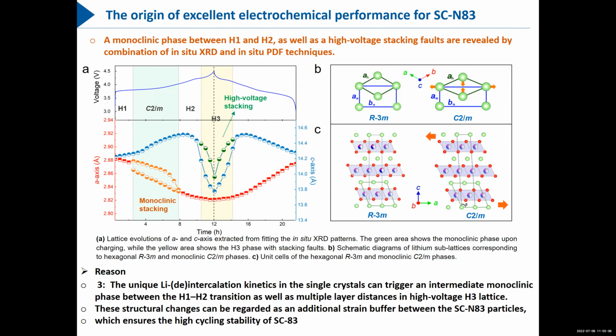So what is the reason for these two phase transitions? Now we know that if the phase transition goes from the H1 phase to the H2 phase, the lattice parameter change is huge. If it changes directly from H1 to H2, the lattice parameter change is very huge, and a huge lattice parameter change just means huge microstrain. So we believe that if there is an intermediate monoclinic phase between the H1 phase and the H2 phase, the monoclinic phase could be regarded as a strain buffer between them.